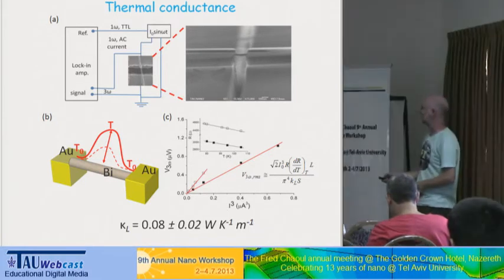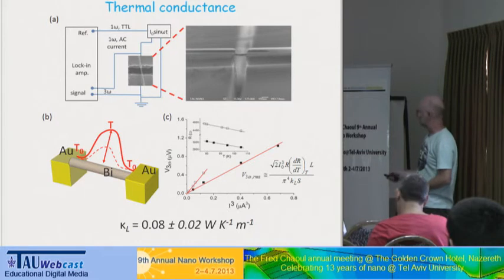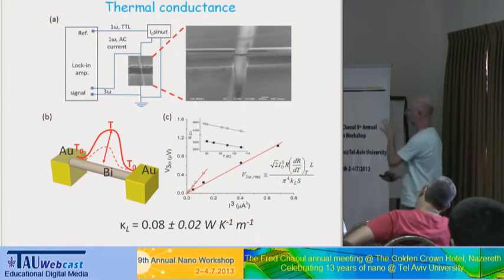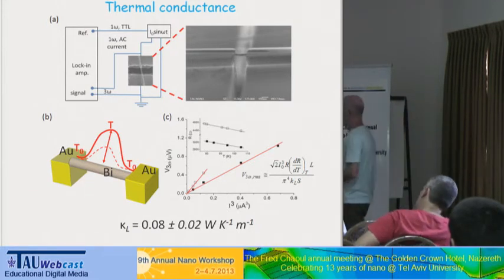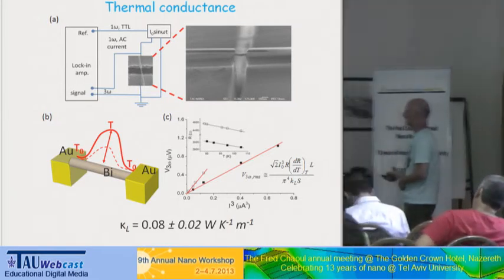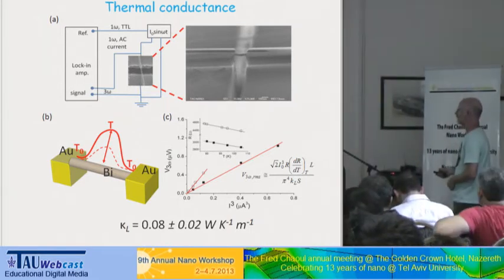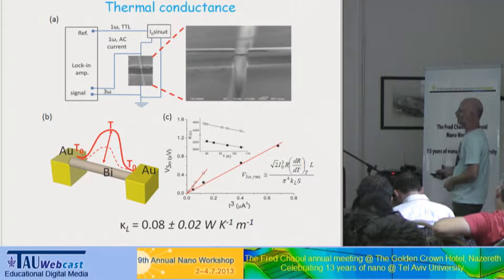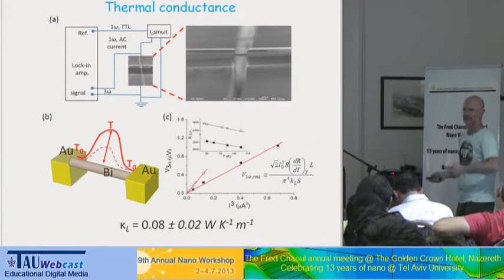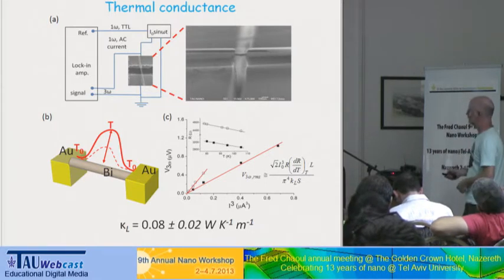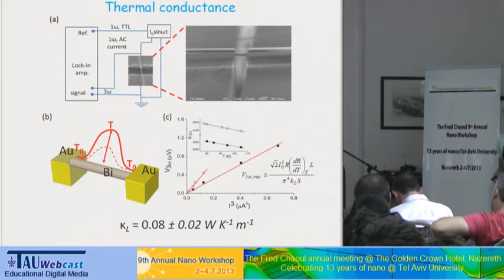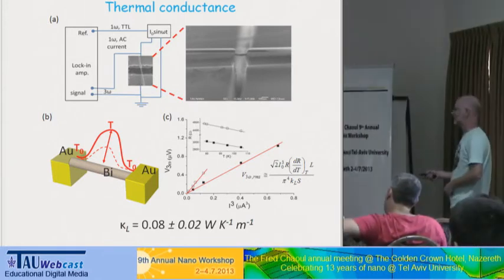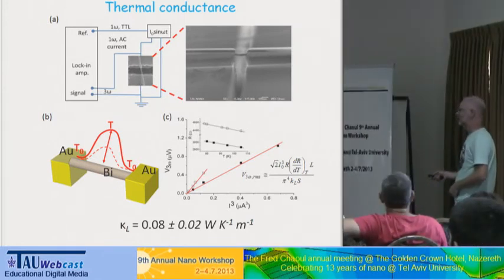So we are measuring 3 omega as a function of the current that is flowing, and you can calculate what we expect the V3 omega to be as a function of the current. This is a one-dimensional diffusion problem of heat through the wire. This is what you see here, the two wires. And this is the thermal conductivity that we measure. The thermal conductivity we extract from these calculations and experiments is really low.